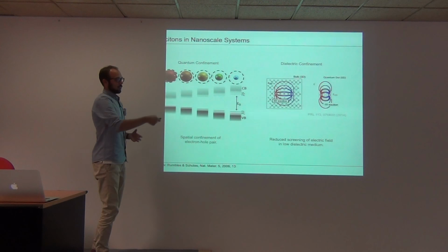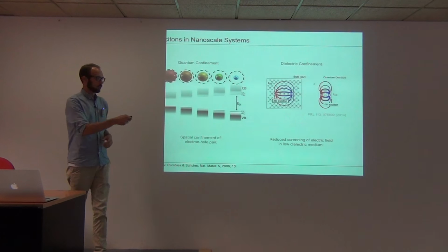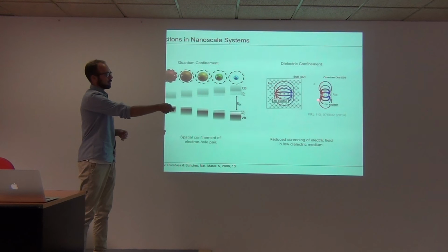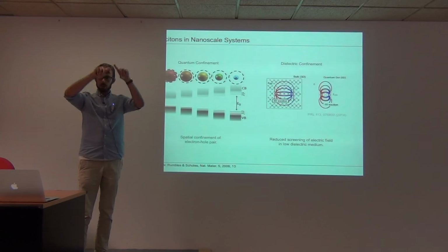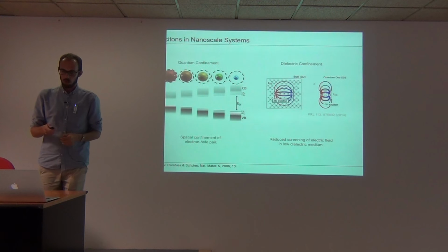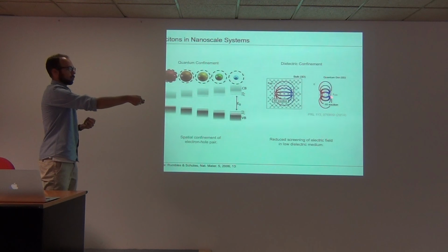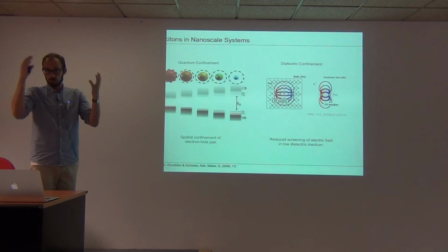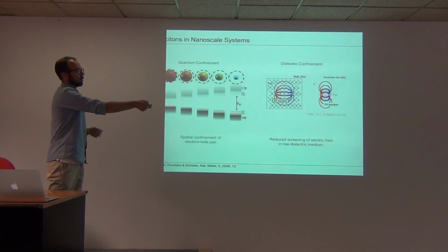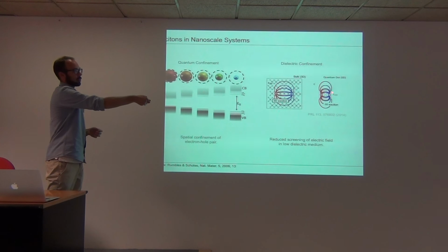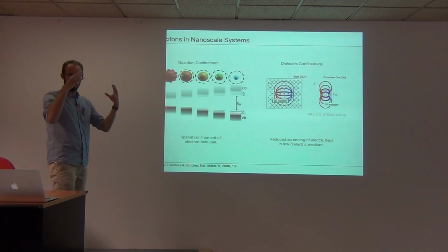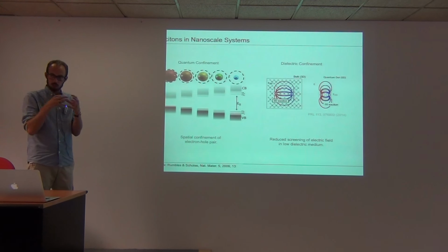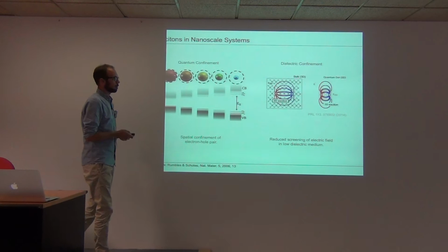If we draw these field lines in a large bulk material, then basically these field lines will see the same dielectric constant all throughout. Whereas in a tiny particle, these electric field lines are now extending beyond the size of the particle. So we need to be careful, when we are describing these kind of excitons, to take into account, let's say, the effective refractive index or the effective dielectric constant of the environment, both taking into account the tiny semiconductor nanoparticle, but also perhaps the more organic environment. So these two effects together lead to this kind of very sensitive tunability of the system.